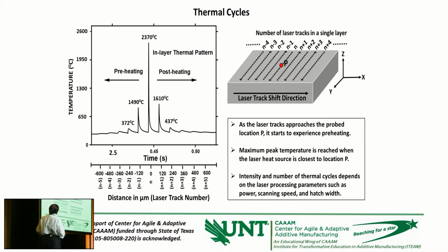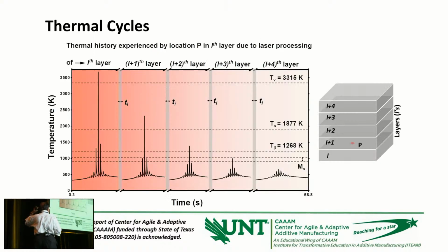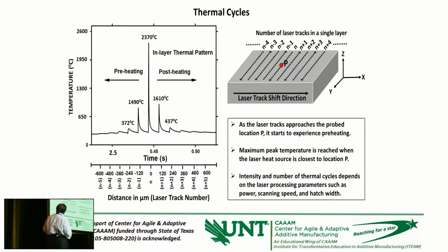So look at this cycle. The temperatures seen for one layer from one point are given here. From this you can see that even when the beam moves away from it, the temperatures created by that beam surrounding this point are still high enough to cause melting in the neighboring track, or high enough to cause solid state transformation. So this is for one layer. Now look at multiple layers. Your computational probe is at the same point in the first layer, and it is now looking at the heating cycles around it, and also above it when the next layer is put above that one.